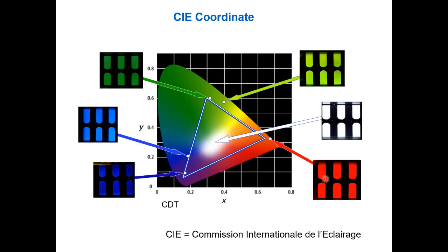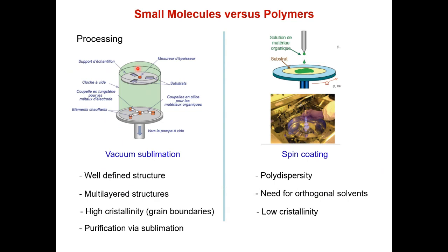So to illustrate those advantages, yes, you can make basically all the possible light you want for a color TV display, just by changing the chemical structure. And you can do the technology with small molecules or with polymers. It's up to the company, and there are pros and cons in each situation. When you do polymers, the best advantage is that you can work with solution. So you can deposit the material from solution. You can print your device on a substrate, which is very neat. But if you need many layers, it will be difficult to stack many polymer layers because there is a risk of dissolving the previous layer that you have deposited.